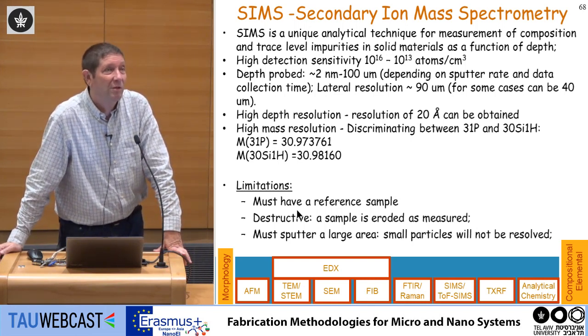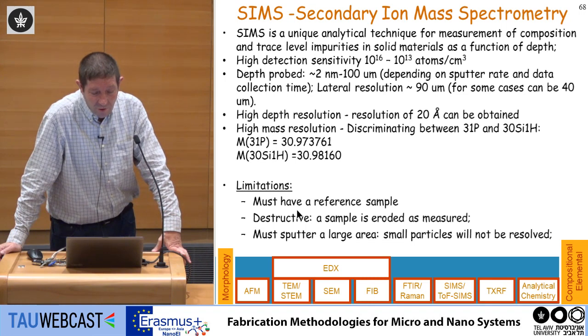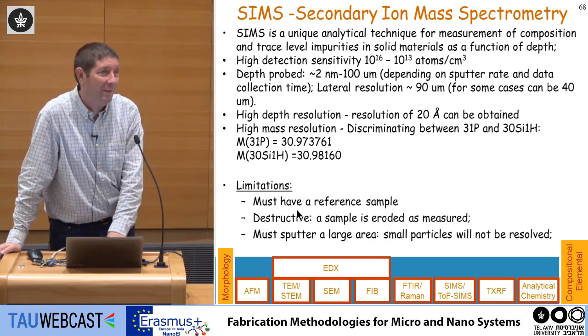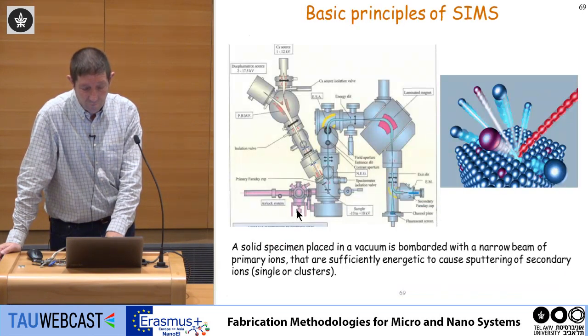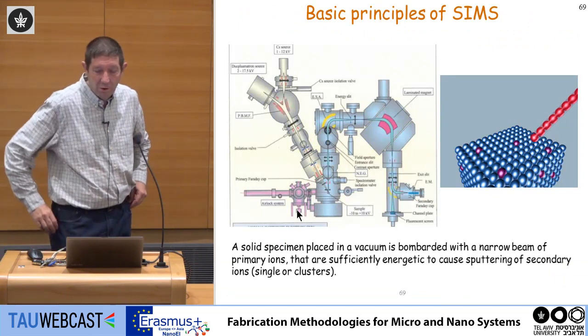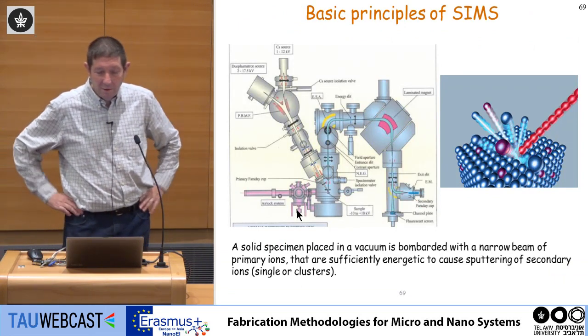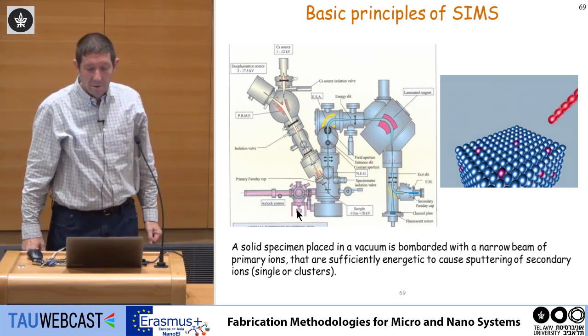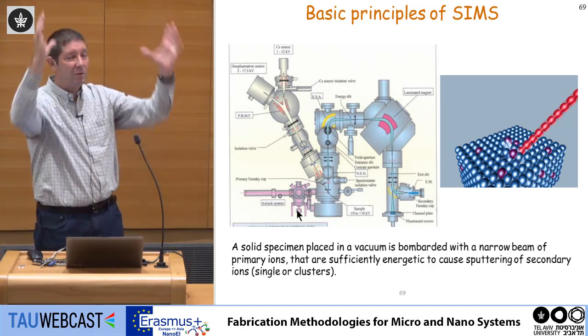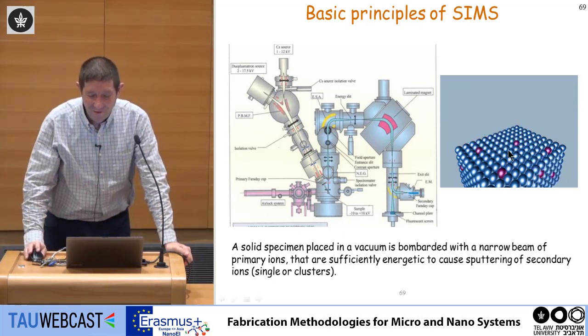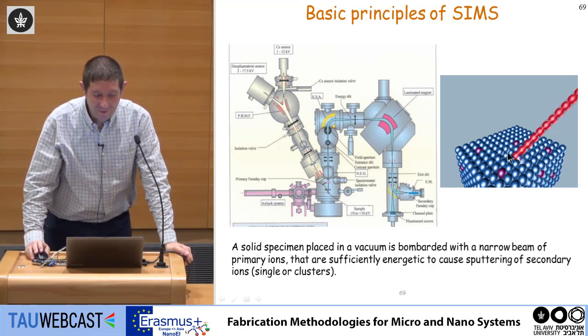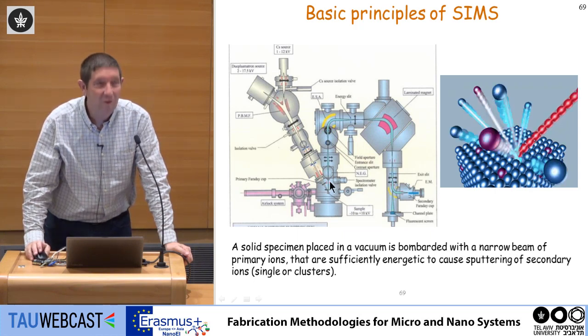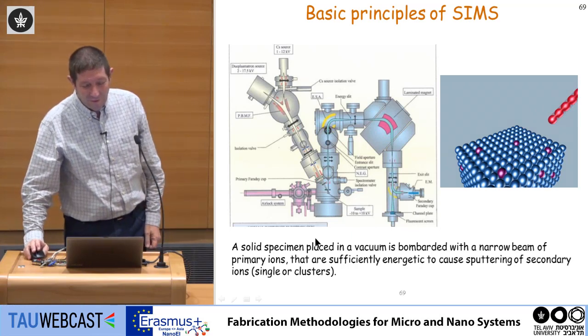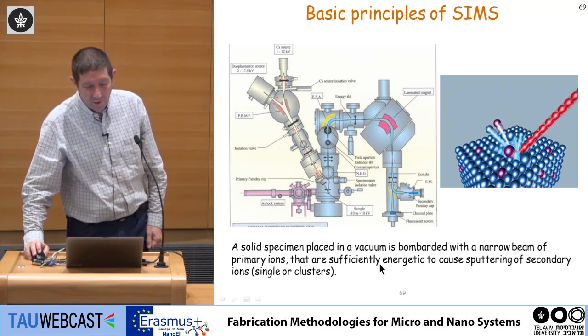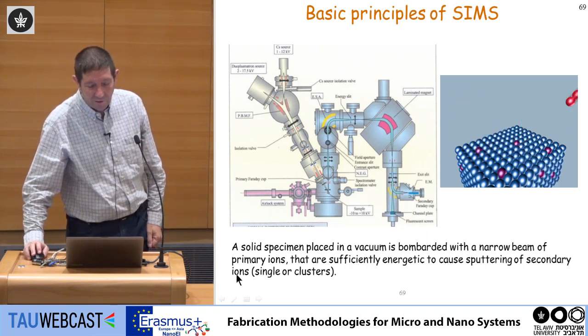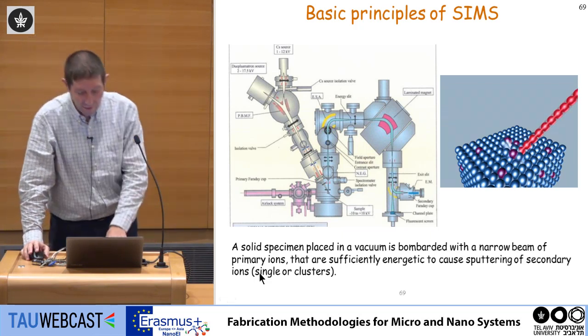It's destructive. I destroy the sample during the measurement, and I must sputter a large area to get a large signal and also to eliminate defects or particles. So the basic idea: I'm shooting with a sputtering material and I look at what's going out. I'm taking an ion, shooting it at the surface, and just seeing what's coming out. Of course, this is a very simple system, a very simple description. The actual system is a very high vacuum system, which can cost a few million dollars. But a solid specimen is placed in vacuum and bombarded with a narrow beam of primary ions, which are sufficiently energetic to cause sputtering of the secondary ions, and I do measure the secondary ions.